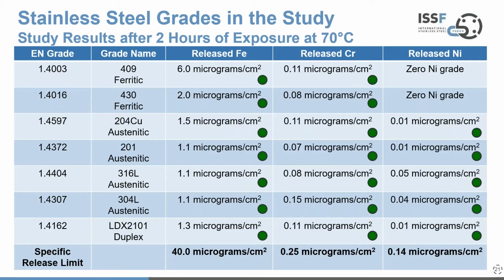So it showed that the metals are only released in very low levels. And I'd now like to illustrate that with the findings for 3 metal constituents: iron, chromium and nickel. There are 7 different stainless steel grades that were in the study. 2 of them, the first 2, the ferritic grades, had effectively 0 nickel, so could not be assessed against the nickel release component. But what you will see, looking at the bottom particularly, the specific release limits of 40 micrograms for iron, 0.25 micrograms for chromium and 0.14 micrograms for nickel, and this is all micrograms per centimetre squared,